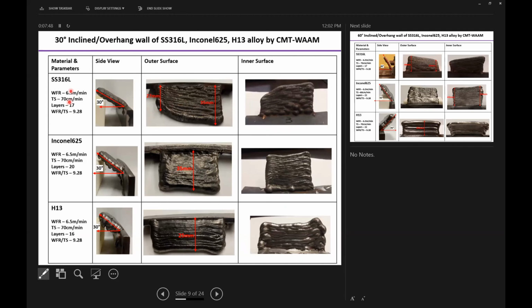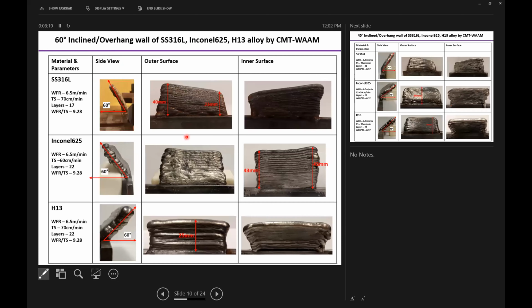So now I will go through some of the incline walls that we have deposited in our lab. Firstly, we started with a 30-degree incline wall, using SS316L material, Inconel 625, and H13 alloy. These are some images, inner and outer surface images, of these structures. Here we use a wire feed rate to travel speed ratio of 9.28. Similarly, we deposited 60-degree incline overhang structures with the same wire feed to travel speed ratio of 9.28 for these three materials.